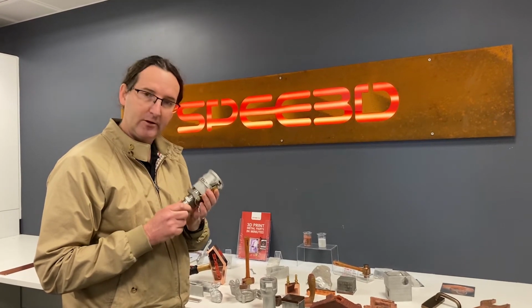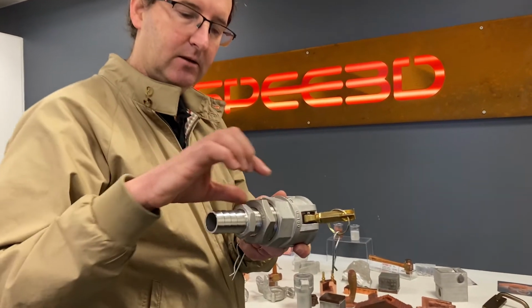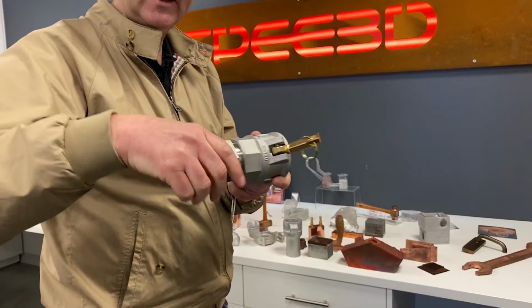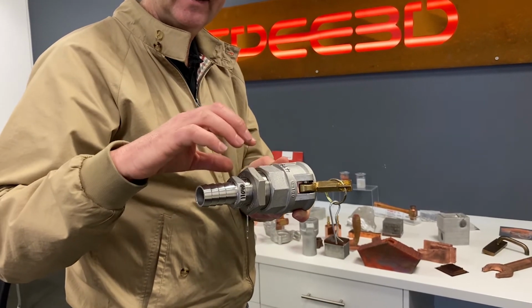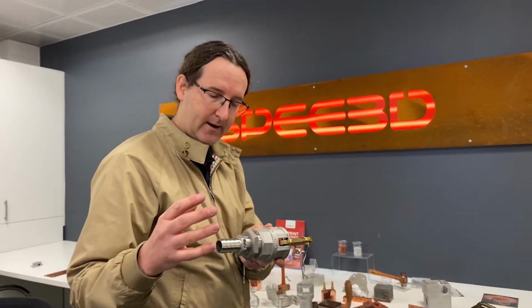This is made out of aluminum. You can see here, it's what they call a Christmas tree. That's aluminum followed by 2 stainless steel fittings. What happens is there is an issue at the junction between the aluminum and the stainless steel, and you get a corrosion point, and these aluminum fittings then corrode out.